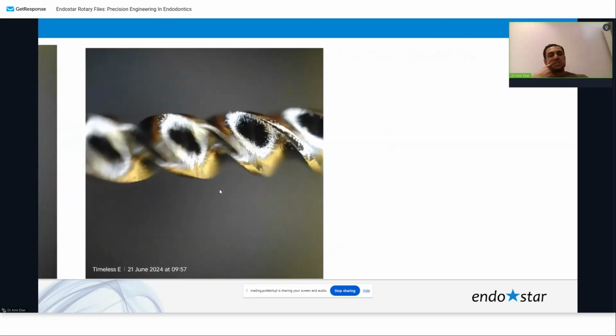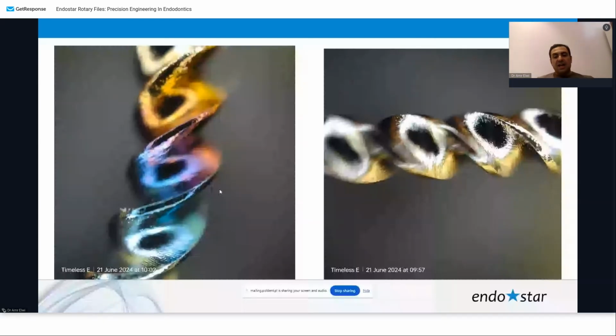So let's make it easier for you. As you can see in the right image, I did this experiment myself. This is a non-heat-treated file. This is an old ProFile which is not available in the market anymore. With no measurements, I heated the file for different times, as you can see, but at a very high temperature, even more than 500 and 700, for a few seconds. But here less than here, and here more. So each millimeter has different mechanical properties.